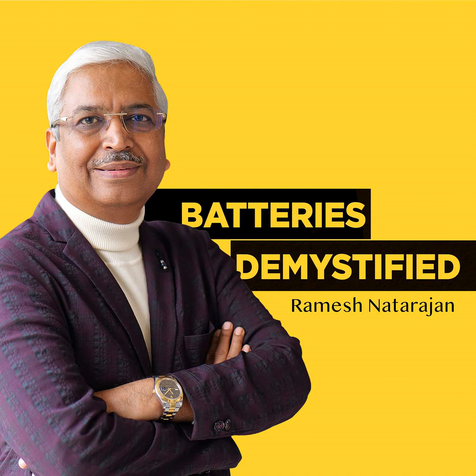But when you imagine you have a very small dose of organic material that you've dispersed in this very large amount of lead, there really aren't any techniques available where you can monitor or measure the amount of lignin that's there. We know how much we start with, but as the battery is cycled, we don't know how much remains. So our process is we're harvesting these grids and using neutron scattering to measure the concentration that remains. And from that, and the amount that's in the electrolyte, we can infer what's happening to the organic as we cycle these batteries at different temperatures and conditions.